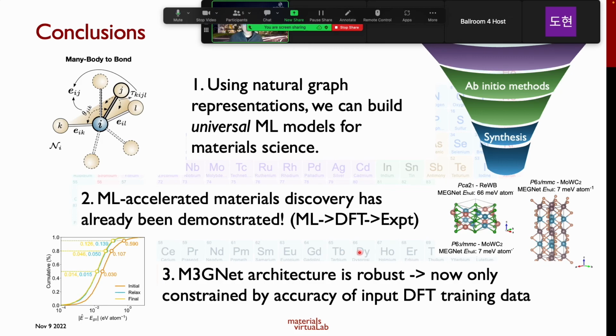To conclude, using natural graph representations, we can build universal machine learning models for materials science. We can use them for property prediction. We can also use them for interatomic potentials. Machine learning accelerated materials discovery is a reality, and it has been demonstrated, as I showed in my example of the ultra-incompressible materials. We have built this universal potential formalism called M3GNet that is very robust. I only showed a fraction of the validations that we have done. I welcome everyone to try it out and test it, and if you find any problems, do let me know. Right now, all that we are constrained by is just the accuracy of the input DFT data.